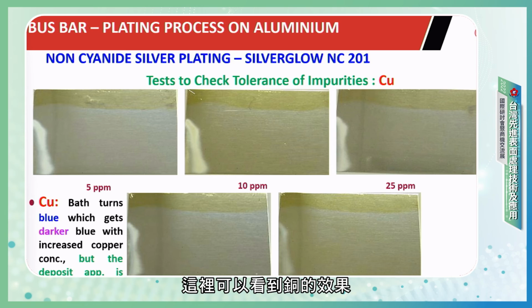Here you can see the effect of copper: 5 ppm, 10 ppm, 25 ppm, 50 ppm, and 100 ppm were deliberately introduced. What we observed is that the bath turns bluish, darker, but the appearance of the deposit is not changing. So an interesting thing is that someone at the user level can even identify that the solution is getting contaminated with copper just by seeing the change in appearance of the bath. But the process has tolerance where performance is concerned, up to 100 ppm, no issue.